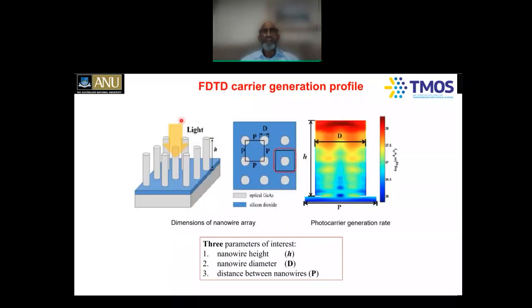Again, we've done a lot of simulations of what should be the height of the nanowire, what should be the diameter of the nanowire, and what should be the distance between the nanowires, or the pitch. You can see that most of the current is generated at the tip of the nanowire, where the high current is the red one and the low current is the blue one. So that means you don't need to make very long nanowires, and particularly for gallium arsenide or indium phosphide, 1 or 2 micron long nanowires are more than sufficient.